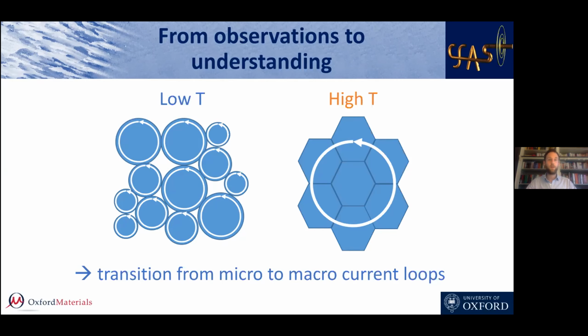Does this matter? Well, yes and no. Yes, because we would like to know what the intrinsic JC is, but no, because in our case, the application is to make a bulk magnet that traps as much flux as possible. So what we care about is just the macroscopic performance. In fact, what's relevant in our application is the macroscopic JC, not so much the intrinsic one. And this was just to start with the basics.